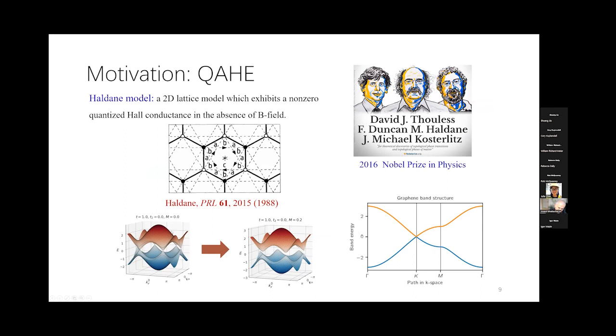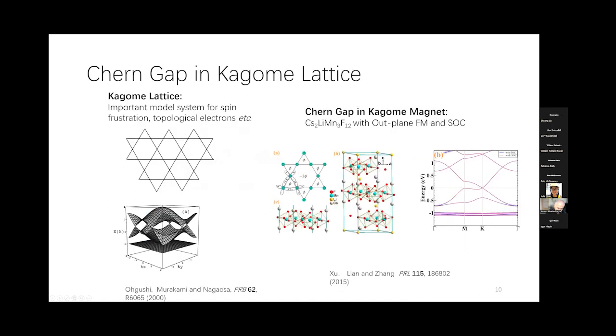On the other hand, if you consider a two-dimensional honeycomb lattice, including the spin orbital coupling and time reversal symmetry breaking, the Haldane model suggests that you will also have a Chern gap opening at the K point. And if the energy is on this point, you see a quantum anomalous Hall effect as well. Because honeycomb lattice is relatively rare in solids, we consider its line graph lattice, kagome lattice. Kagome lattice is a highly frustrated lattice, which has potential to host some exotic state like quantum spin liquid.